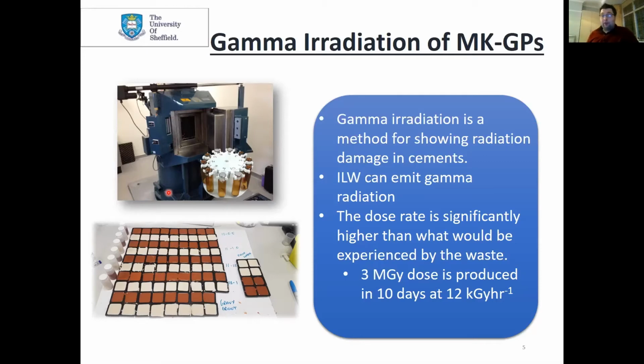We achieved 3 megagray. This isn't a lifetime dose of the samples, but it's close and fairly representative. It's also 3 times whatever anyone else has published in the literature. So this is really interesting.